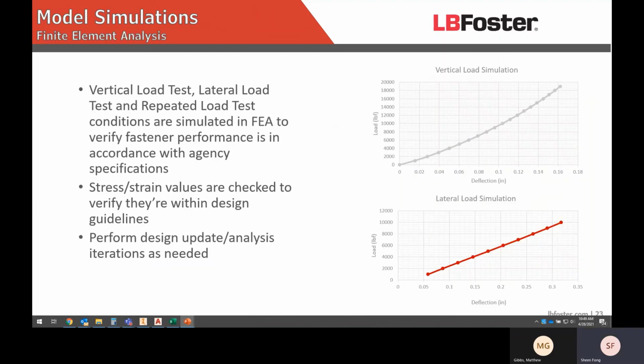And from there, we will develop a 3D model and load it into our FEA software, which will predict our vertical and lateral stiffness, and also let us know peak stresses and strains during the repeated load test, which is a fatigue test that will determine if we can make it through the 3 million cycles. We also perform iterations as needed. If the strain values are too high or the stresses in the plates are high, we'll make design tweaks and run the analysis again.